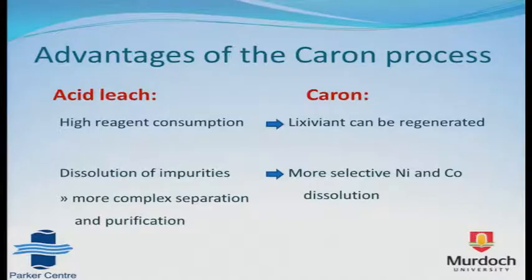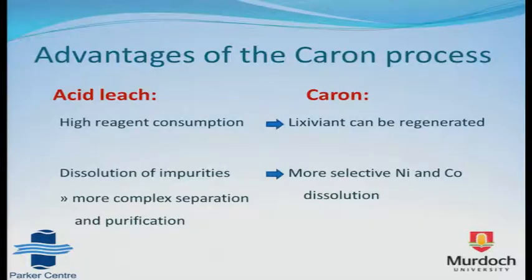Therefore, generally, laterite ores are usually extracted using acid leaching techniques. However, the drawbacks of the more common acid leaches are the high reagent consumption due to the presence of acid-consuming species and the dissolution of high amounts of impurities which make it more difficult to separate and purify the final product. The Caron process overcomes these two main drawbacks of the acid leaching techniques by using a lixiviant that can be regenerated and recycled into the leach, therefore reducing the expenditure due to reagent consumption. And also by employing a more selective lixiviant, so it targets more specifically the metal values with less dissolution of impurities.